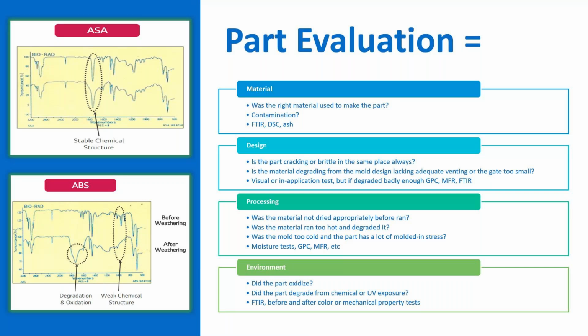Was the material run too hot? So did I degrade it because I ran it hotter than I should have? Was the mold too cold and I put in a lot of molded-in stress? So again, did I freeze it too quickly before it could crystallize? That's a problem. So stuff like your moisture test, GPC, FTIR, etc.